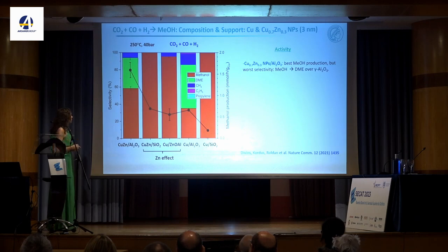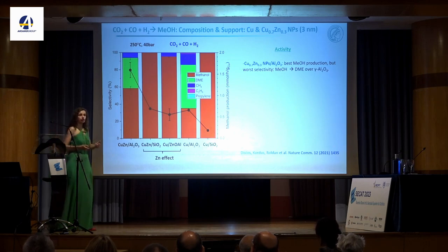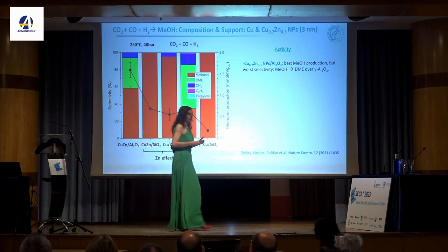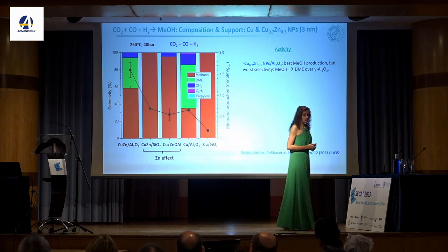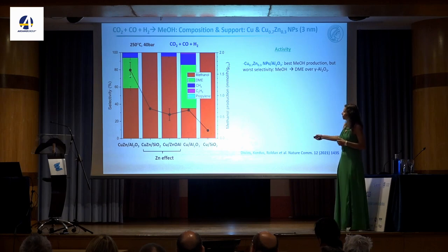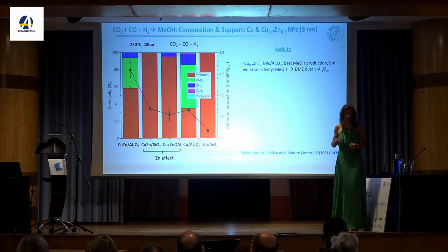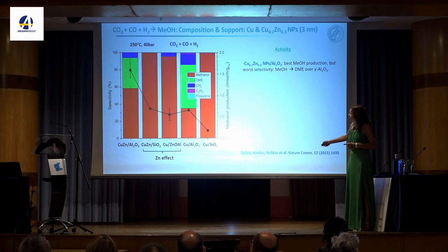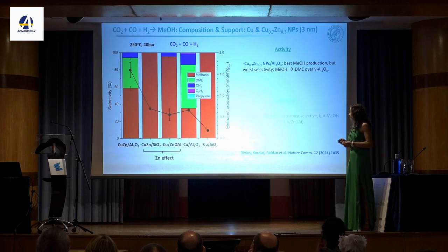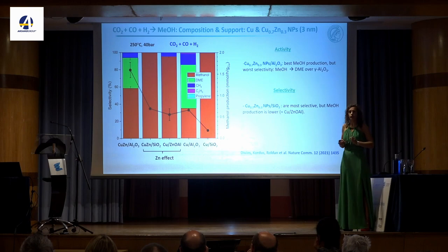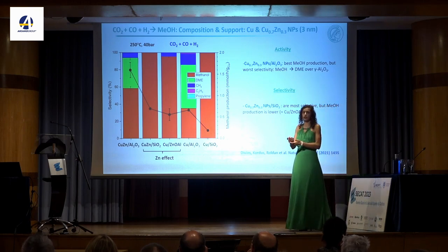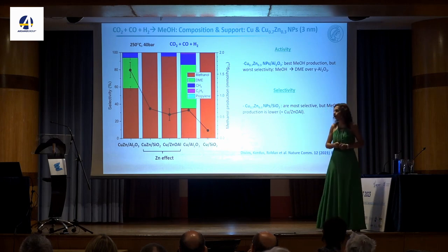This is making methanol. And if you put the same copper zinc nanoparticles, instead of on silica, on alumina, we see that it becomes much more active, but unfortunately, we start changing the selectivity. We start making the dimethyl ether. This is not surprising because this happens on the alumina side, but you can play with the ratio of how much methanol versus the dimethyl ether you are making by tuning the content of zinc in these copper zinc nanoparticles. And I will tell you a little bit more about this in a minute. And if you take the same particle size, but you don't have zinc, you see that there is a much less active system. So from this type of studies, we could learn the support matters, but you don't need the zinc oxide as part of the support. You can just put it as part of the active component within the nanoparticles.